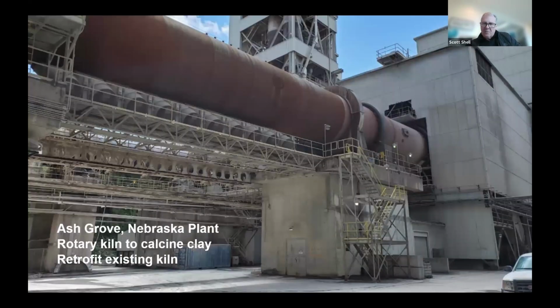I'm going to show you three different ways to make this LC3. The first one is you make it in a rotary kiln, just like you make cement. In fact, this is a former clinker rotary kiln for the Ash Grove Cement Company, a subsidiary of CRH, in their Nebraska plant. They are actually retrofitting this kiln to calcine clay instead of to make clinker. It's very low cost to retrofit it.